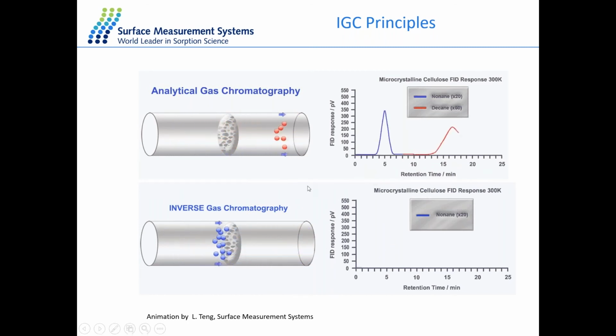However, inverse gas chromatography is a little bit different. What we're doing is packing the column with your sample of interest, and then injecting individually a few probes with known properties. On the detector end, we will end up with peaks based on different retention times, and this is a result of the interaction between the probe molecules and the sample of interest.